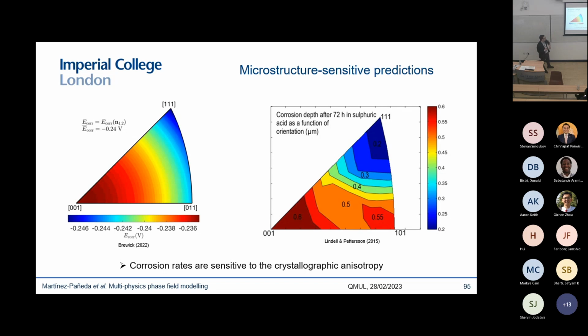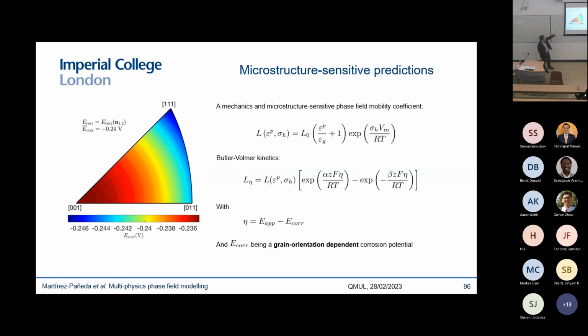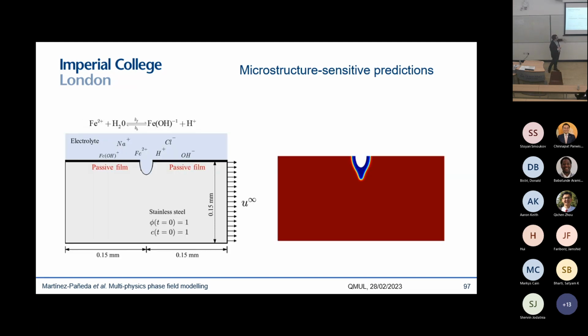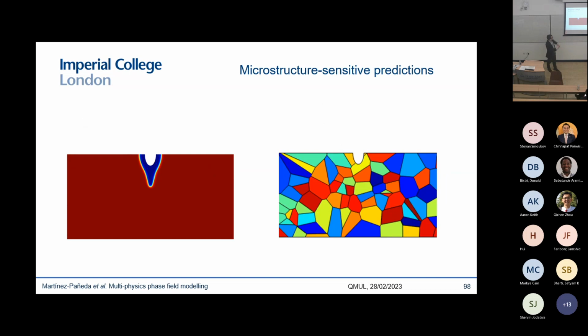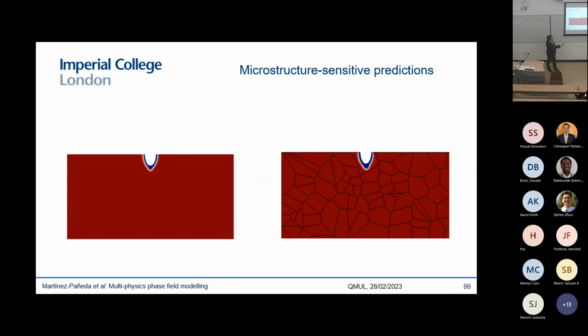For example, the role of the microstructure. The microstructure will play a role because you have some anisotropy not only in the mechanical properties but also in the corrosion behavior. We have seen this experimentally, and we can easily incorporate that into our model by defining a new mobility coefficient. And you can see here some examples: this is an isotropic case, and this is a case where we introduce a microstructure, and you can see how you have a different behavior when you take into account the microstructure.